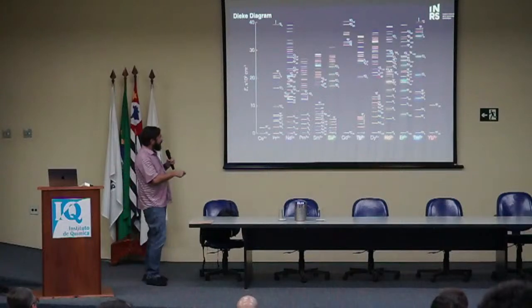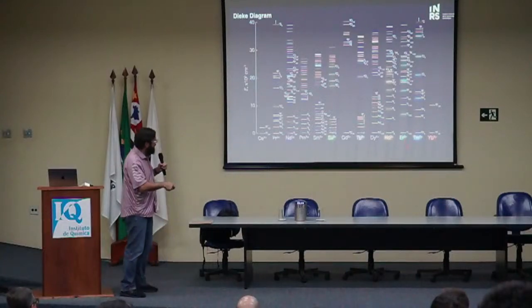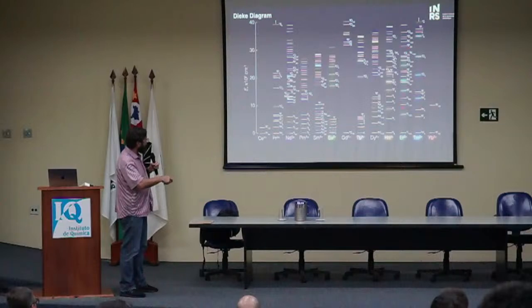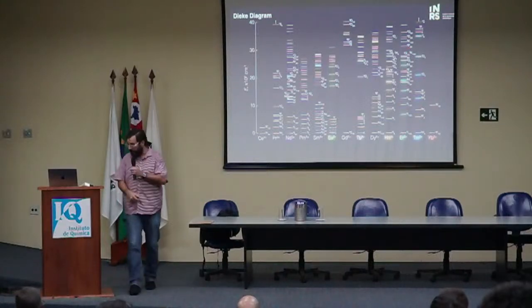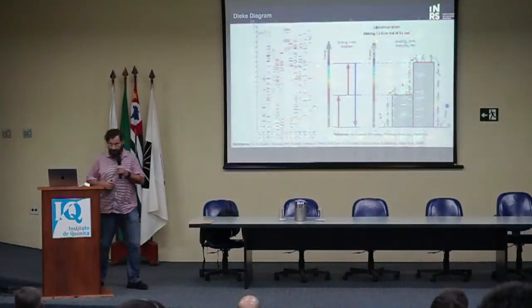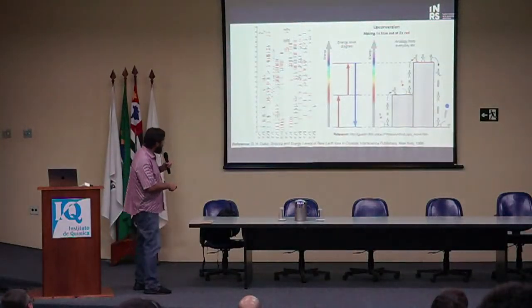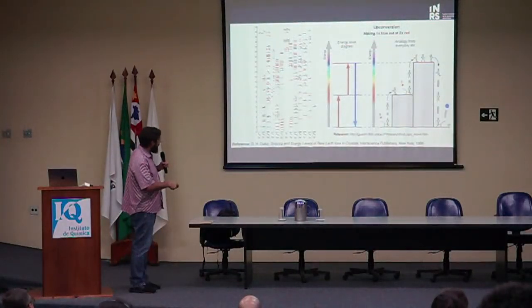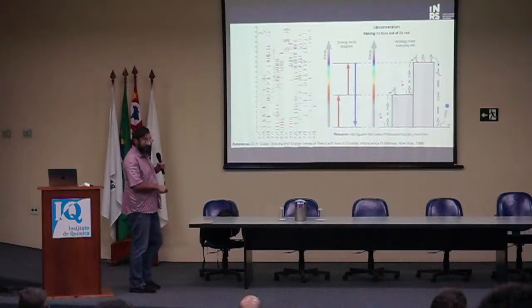And you see that there are very many states, very close together. So if you take an ion like, for example, erbium, let me go to the next slide here. If you take an ion like erbium, you see a ground state here. There's an intermediate state about there, which would be this one. And then if you go up this ladder, there's another excited state about there, which will be this one here. So the energy between the ground state and the intermediate state is pretty much equal to the energy between this intermediate state and this upper state.